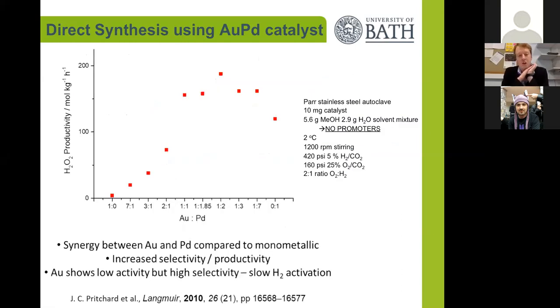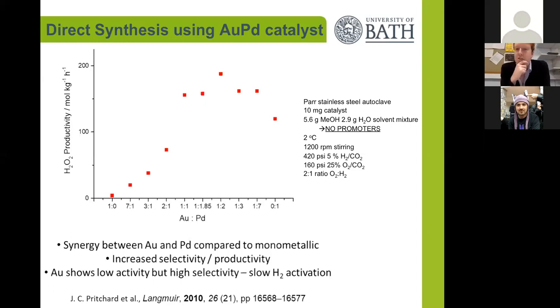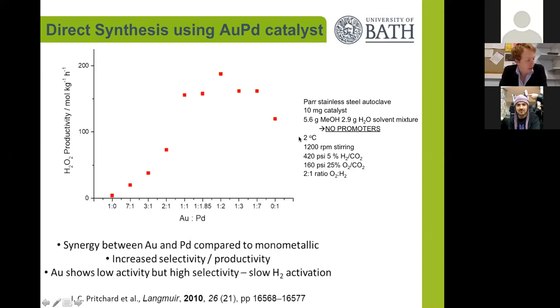Testing these carbon-supported particles under our direct synthesis conditions: typically we use mixtures of alcohol and water as a solvent. We add the alcohol to enhance the solubility of the gases in the solution. We don't add any acid or halide promoters to our reactions.